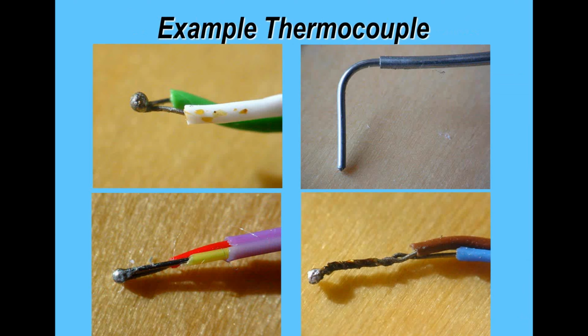Here is an example of a thermocouple which is of no use whatsoever. You'll notice that the wires coming away from the thermocouple junction are twisted together. Now, what you're getting there is intermittent measurements. So if you've got a profile and you've got lots of squiggly lines on your profile, this is one of the reasons you get that, where you're making intermittent contact and not actually monitoring the junction temperature. The temperature is monitored at the point that the two are brazed or welded together. If you twist the wires, like you see here, you get intermittent measurements, so it should be avoided.